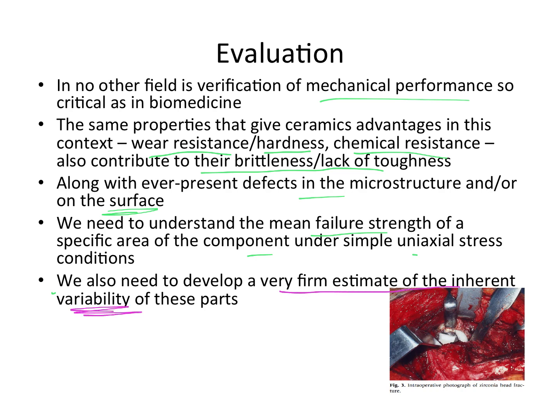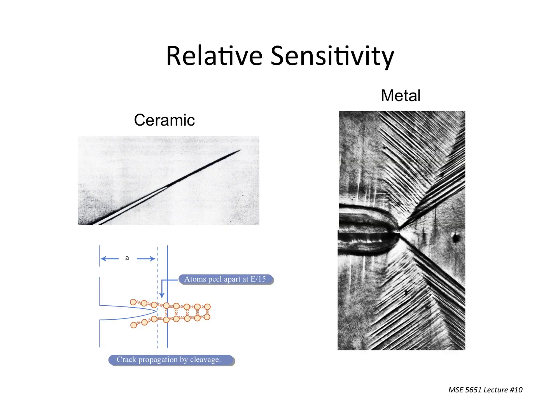And so I just reprised this image of what happens when these things fail in vivo. This does happen, and we know why it happens. We want to minimize the fact that it happens, but we also want to account for the fact that we know it's going to happen and try to make predictions about these things. And so what we do is we first consider what's going on in these systems. This other image is showing you a nice metal with a flaw in it, and when it reaches a certain stress on that flaw, what are these things that shoot out from that defect? The word most ceramics people don't like.